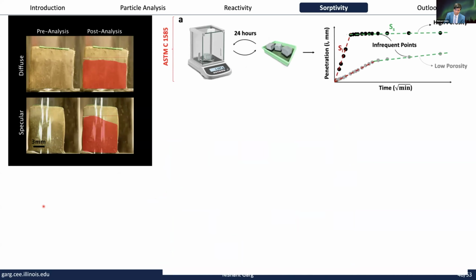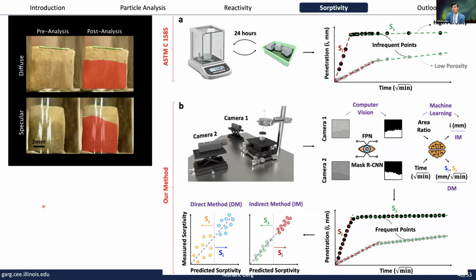And what we're able to do with this approach is see in real time, again, that waterfront as the sample is absorbing water. Now, these are highly sped up videos. This process takes maybe several hours to several days. And by doing this, we can now measure this water ingress very frequently, almost in an automated way. You can record a video over several days if you want, as opposed to using a human, who is only going to take certain weight measurements.